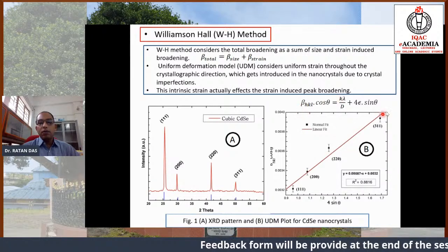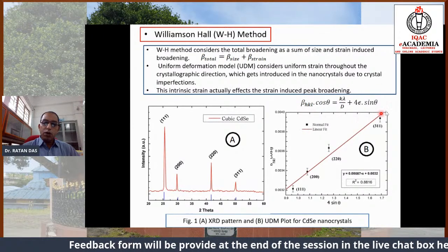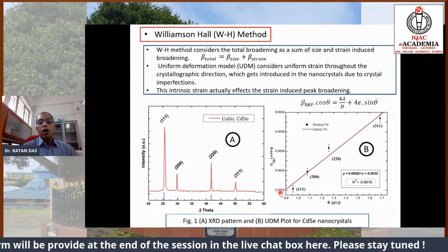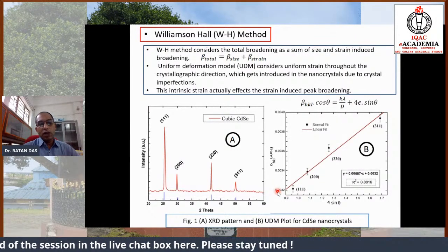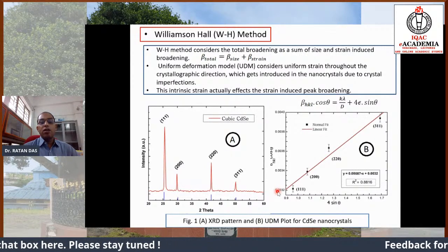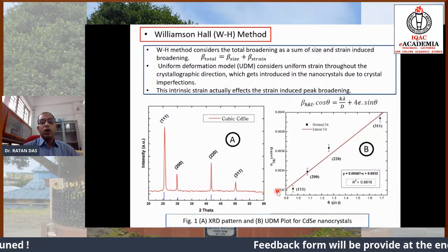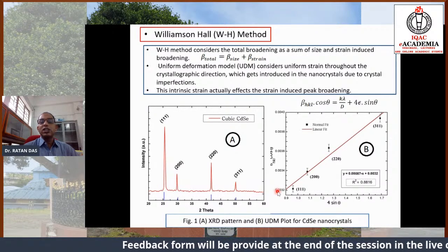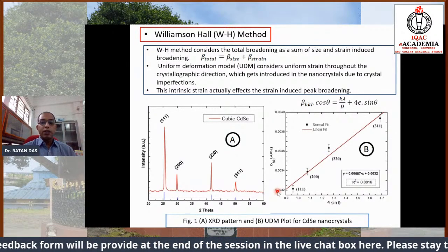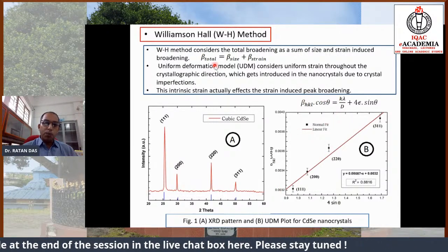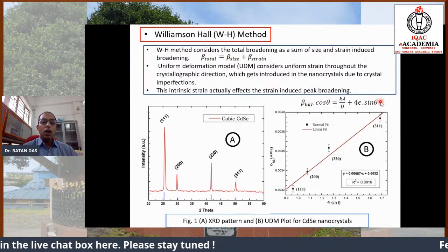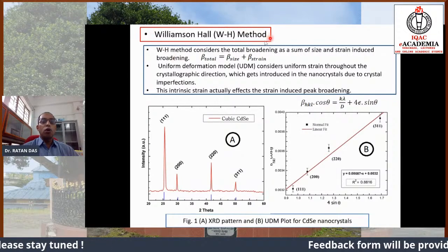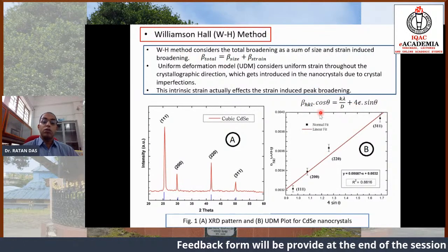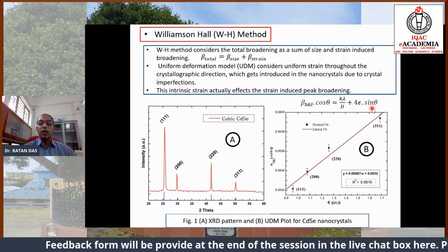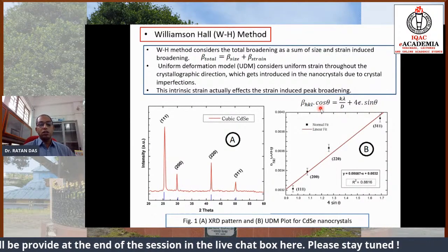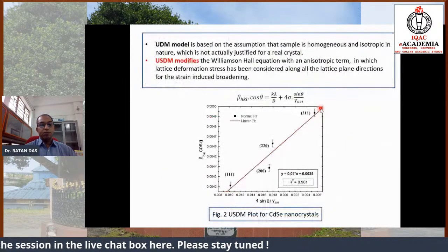What I want to say is that this particular simple method provides the size as well as the strain. It is found that later, if we find out the size and strain by other different methods, the obtained values are almost matching. That signifies that the Williamson-Hall method is one of the simple and best techniques for obtaining size and the intrinsic strain value inside the nanocrystal.